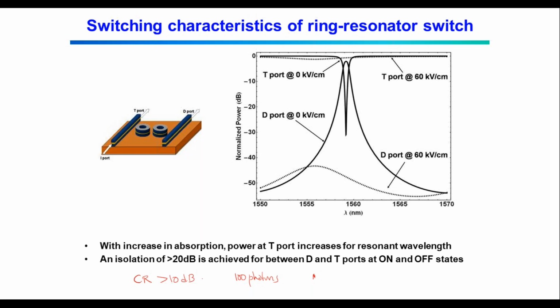Now I said that you can switch the signal. I'm putting the resonance signal, lambda naught, here. This lambda naught will appear either at the drop port or at the transmission port. So how do I do that? I apply an electric field. By applying an electric field, I can change delta alpha, which is called electroabsorption. By electroabsorption I can make the lambda, instead of appearing at the drop port, appear at the transmission port.